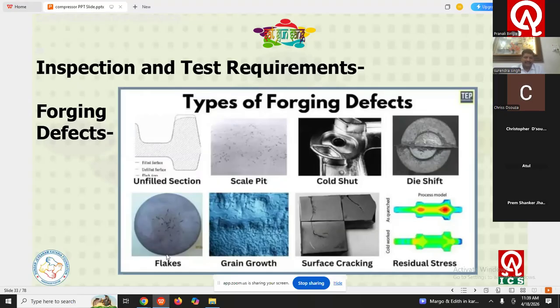Flakes may be there. Grain growth, this defect may be there, and we can capture it through the microscope. Surface cracking may be there, so you can see that the cracks are there. Then the residual stresses are there. So these are the forging defects that may occur in the forging. But first we must be aware of which kind of forging defects come in the forging parts.